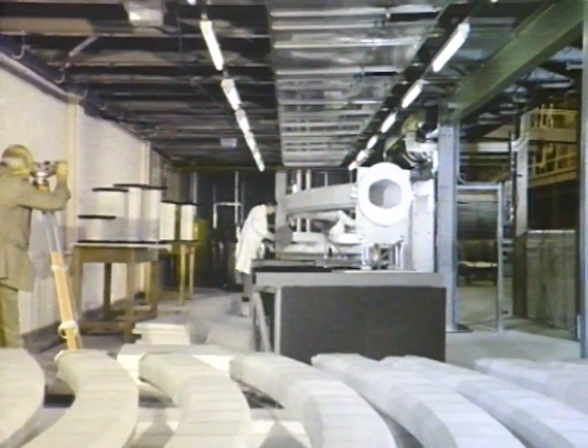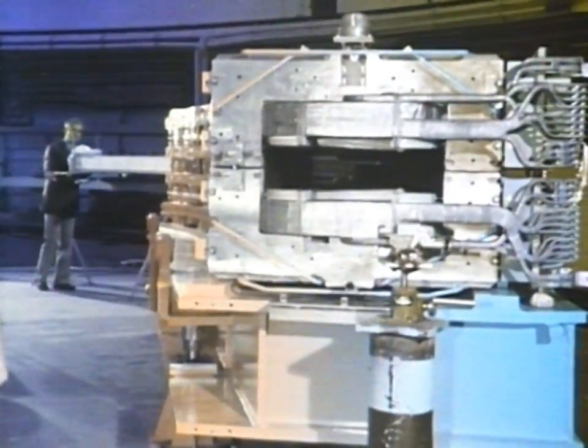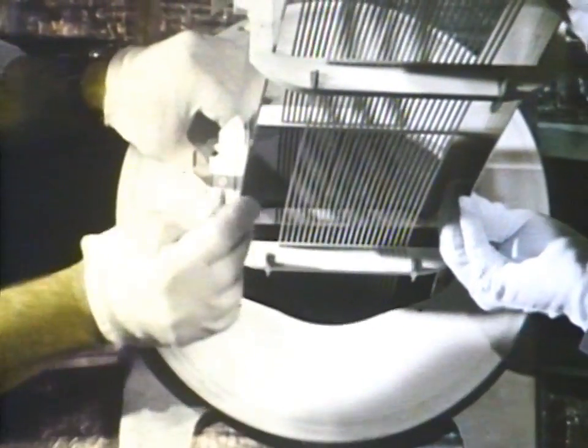Both straight and curved vacuum chambers were produced in this way. The curved vacuum chambers have to be inserted into completed bending magnets so they have large diameter vacuum flanges at one end only, and must be positioned with only one millimetre clearance between the chamber and the magnet poles. Although the use of a ceramic vacuum chamber solves some problems it introduces others — the proton beam must be made to believe it's travelling in a metal tube. This is achieved by a radio frequency shield made of stainless steel side plates with wires top and bottom, supported by frames made from Macor, a recently developed glass ceramic material. The shields were one of the most difficult design problems encountered, and insertion of the five metre long assembly into the vacuum chamber also wasn't easy.